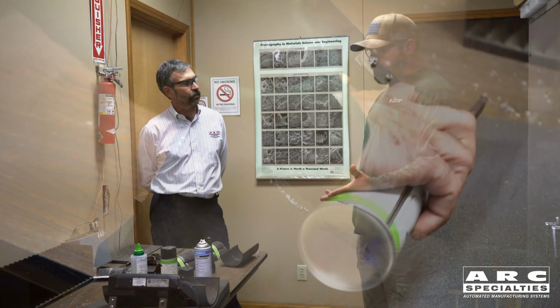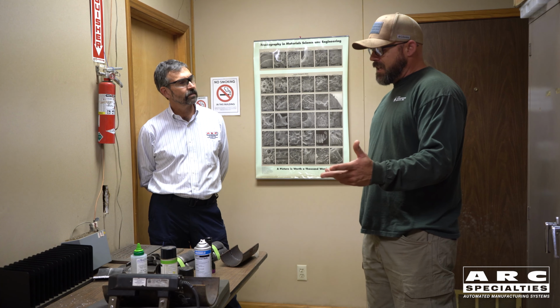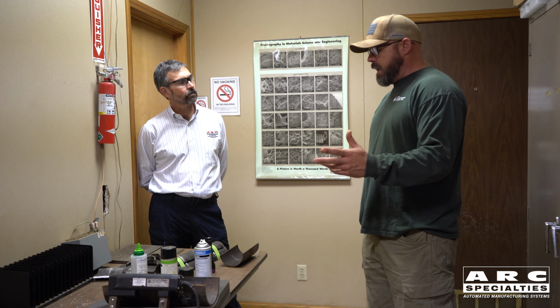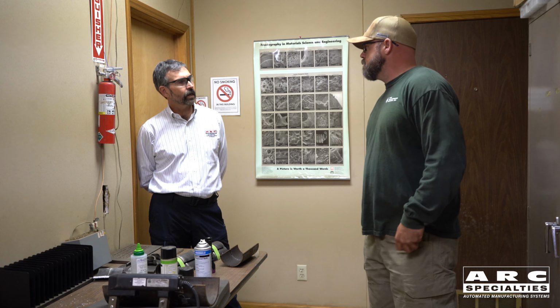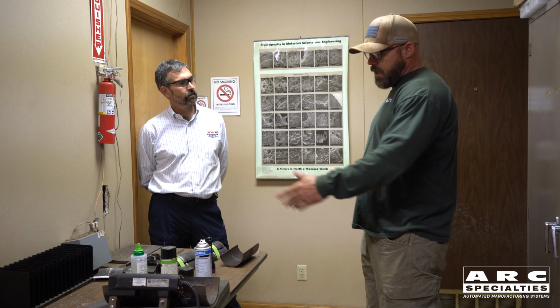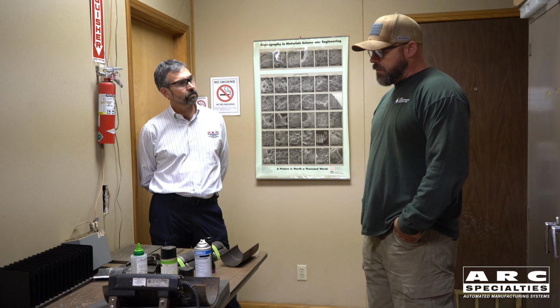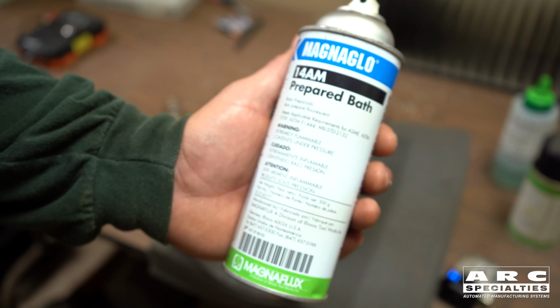What's this used for? It is to detect surface indications that can't be seen with the naked eye. Cracks, porosity, what can you find with this? Lack of fusion. In this case, there's a little bit of lack of penetration. Pretty much anything; rounded indications are hard to see with magnetic particle inspection. Is this one visible or is this fluorescent? This is wet fluorescent. It is a prepared bath.